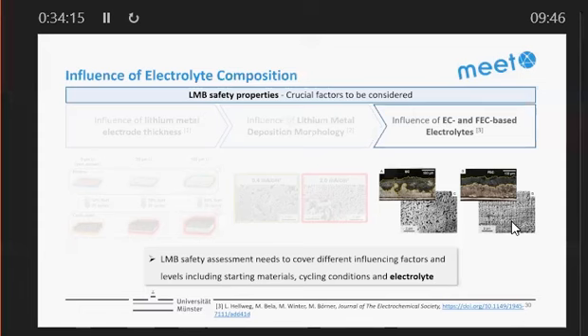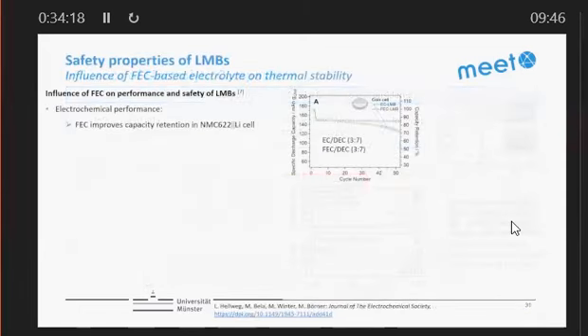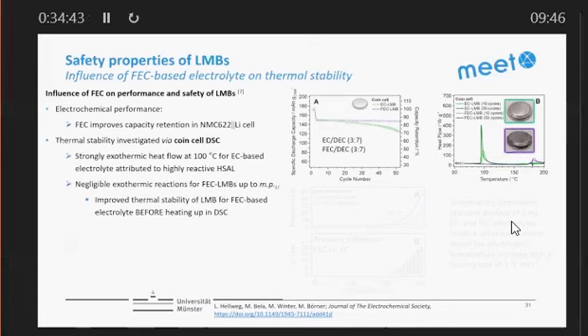Now we look at FEC and EC-based electrolyte. And basically, we are using here an electrolyte with only EC-DEC or only FEC-DEC. So the FEC is not used as an additive, it's used as a 30% component in the cell. And we see with FEC, at least for a given number of cycles, almost no degradation. So FEC is good, and the more FEC, 30% is a lot, the better for lithium metal batteries. If we look at the DSC, we see that with EC, we have an event at around 100 degrees C and less. With FEC, it's flat. That means FEC is not creating high surface area lithium after 50 cycles. So this is actually good news.